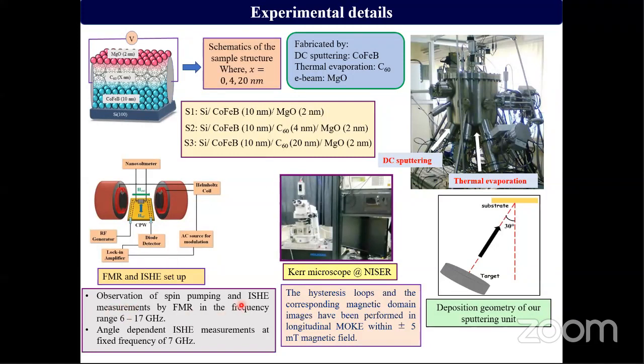So observation of spin pumping and ISHE measurement were performed in the frequency range 6 to 17 gigahertz, and the angle dependent ISHE measurement we have performed at a fixed 7 gigahertz frequency. For the angle dependent measurement, we have rotated the sample at 5-degree intervals. And for the hysteresis loop measurement and the corresponding domain imaging, we have measured using longitudinal MOKE with plus minus 5 millitesla magnetic field.